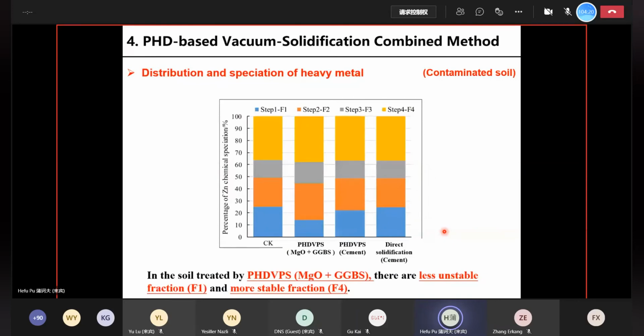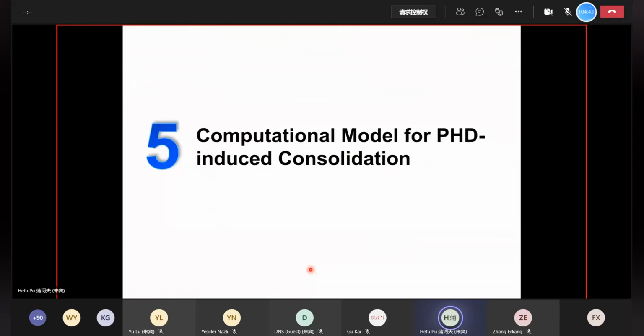The reason is that it caused the change in the speciation of heavy metal. When we treat the mud slurry with the PHDVPS method, especially when we use the MgO and GGBS as a binder, there is less unstable fraction of heavy metal and more stable fraction of the heavy metal. And lastly, I will present some computational model that we developed for PHD-induced consolidation.